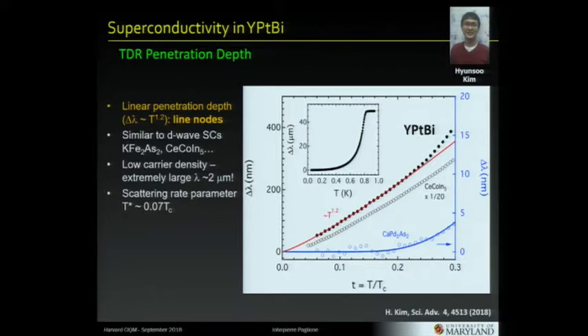So this large penetration depth, the numbers are roughly on the order of microns. That means that the penetration depth is of the order of the sample size, roughly speaking. That makes it also extremely hard to do things like NMR or study vortex physics, because the vortices are essentially huge, right?